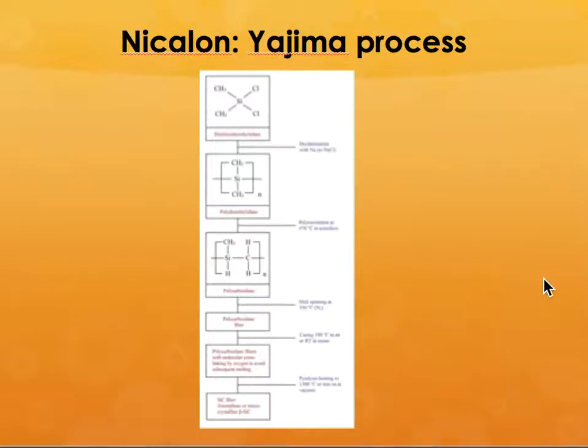One of these processes is called the Nicalon or Yajima process that was developed in Japan. Now, the problem in those days was that the silicon carbide fibers that were produced were not very pure. So they did not withstand the processing temperature, and would get attacked. So it was not a very good process, but now they seem to have overcome those problems, and they are producing much better fibers.